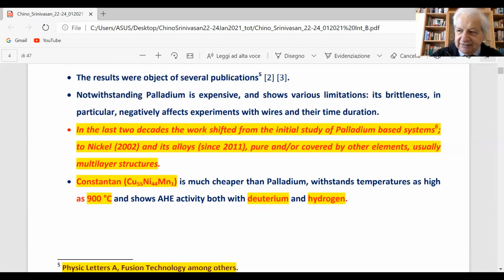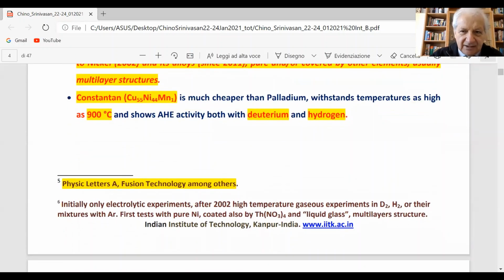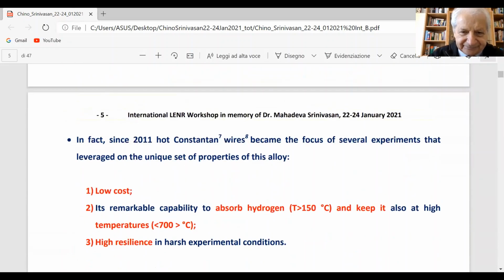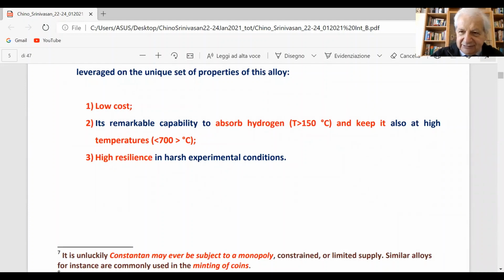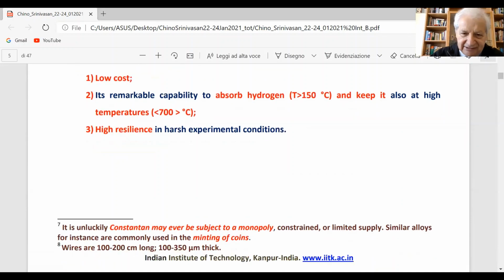But luckily in 2011, we started a new material, constantan, a copper-nickel alloy, that has lower cost than palladium, and moreover is mechanically stronger against hydrogen embrittlement. And it can work up to very high temperature, 900 degrees, important from the technological aspect. Constantan absorbs hydrogen starting from 150 Celsius, so it is a very easy procedure to check if the material is good for our operation. And it keeps up to 700 degrees, at least in our tests at low pressure up to 4 or 5 bars. And it has high resilience, which means it is strong against stress for a very long time.